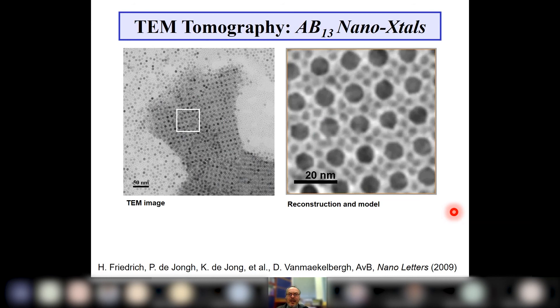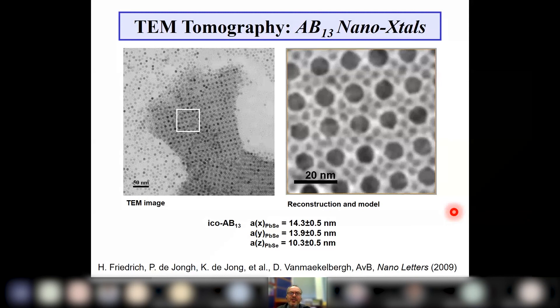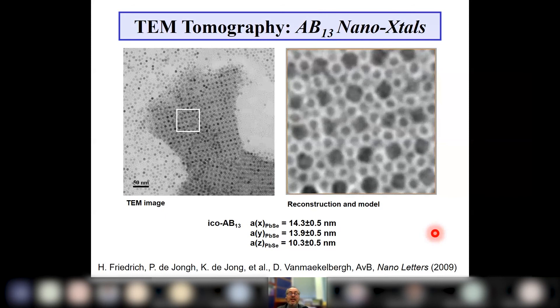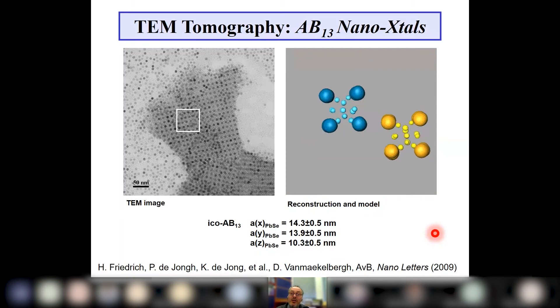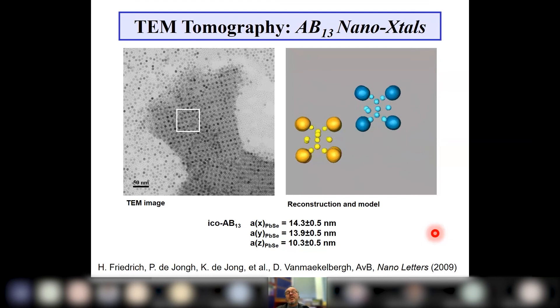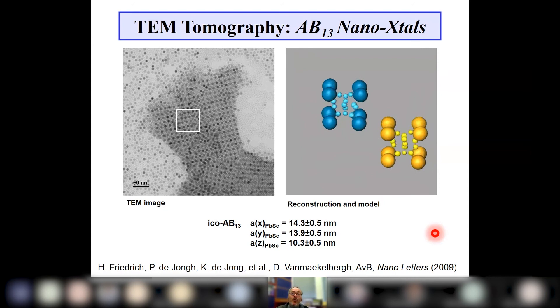In 2009, work done by Heiner Friedrich in the group of Krijn de Jong, in collaboration with Daniel Vanmaekelbergh's group, analyzed a beautiful binary crystal of different-size nanoparticles — the scale bar is 20 nanometers. The simple cubic arrangement of the big particles could be recognized by scattering, but where all the small particles were could not be determined by scattering alone. For the first time, real-space analysis via electron tomography made that determination possible.